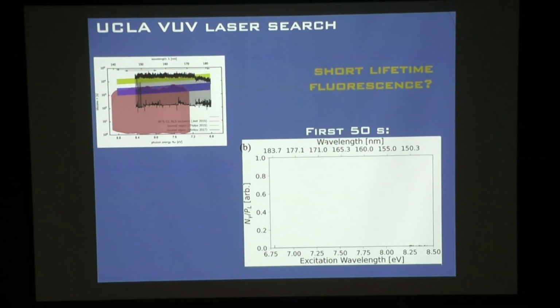And what that looks like, if you look at what we call the short lifetime signal, the total amount of photons in, say, the first 50 seconds, it looks like this. From 184 down to about 160, we see nothing. This is like 2 years of just zero every day. Then around 8 eV, we saw a little bump. But then we put in our thorium-232 crystal, the one that doesn't have the nuclear transition, and we also see a little bump there, so we're not too worried about it. Maybe it's a defect associated with thorium, or maybe it's an impurity, because you could have a little bit. This is not a huge signal, a little oxygen or something in the crystal.